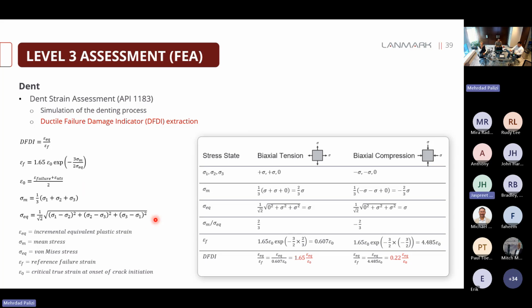So the next step, we're going to do a quantification over the amount of damage during the indentation. This is going to be done with, actually there are more measurements in API 1183. The one that we have here is the ductile failure damage indicator, or DFDI. So DFDI, just like the strain-based failure criteria for corrosion, is also a demand divided by a capacity.